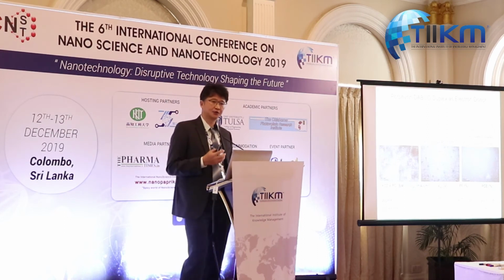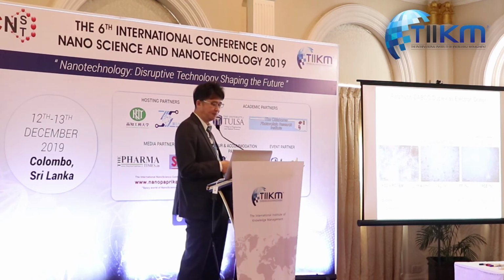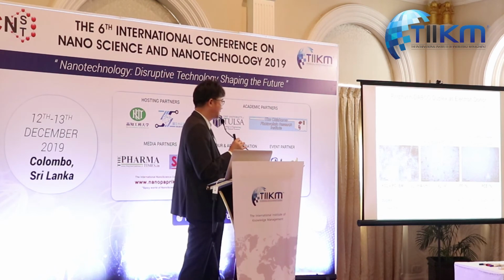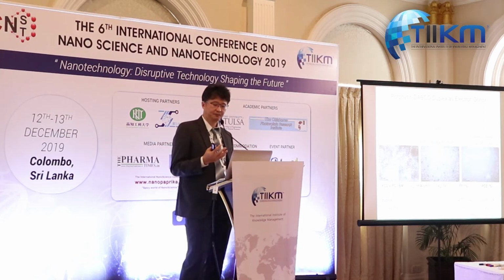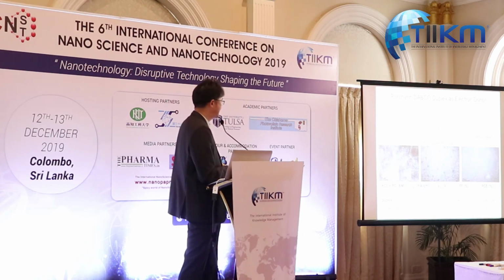Later, we used DABCO to trigger the supramolecular assembly of KC2, forming the KC2 duplex. The TEM image of the KC2:PCBM film shows relatively larger phase separation, whereas the KC2 duplex:PCBM:CN film shows better donor-acceptor mixing, and so the PCE is higher for the KC2 duplex:PCBM:CN.